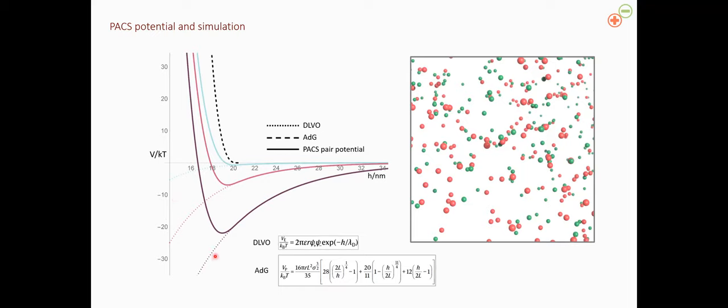And the trend here is that at lower salt concentrations, my electrostatic attraction is deeper. At higher salt concentrations, where the interaction is screened, it's more shallow. And then I have a repulsive potential from the polymer, and this is given by the Alexander-de Gennes model. This is all very long, but basically what it says is that the length of the polymer, as well as the surface coverage, are both very important. And these are actually properties that are in literature because the Pluronic series is so well studied, especially on polystyrene. So we know these values, or at least feel confident with these values.